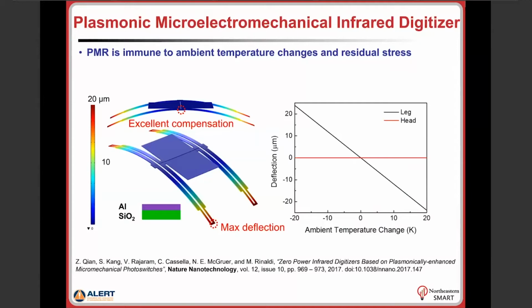So what you can see here is that if we have an ambient temperature variation, for example, both the inner and the outer pair of thermally sensitive legs will bend in the same direction, and that will translate into substantially no displacement of the head of the cantilevers. And then here you see the actual deflection of the leg and the head with ambient temperature change, and you can see that the gap that separates the two contacts does not change at all if there is any kind of common mode variation in this structure. It could be ambient temperature variation, or it could be residual stress in the thin film materials that are used to build these structures. So that's quite important in order to achieve low false alarm rates in these kinds of devices.